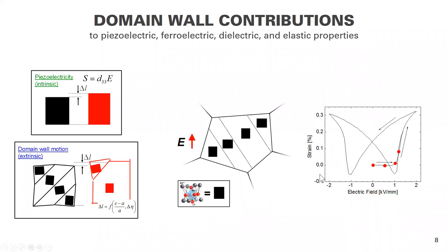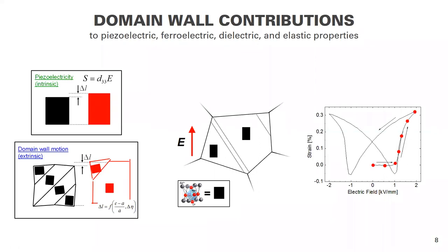And so with a little bit of electric field, not much happens. But as soon as you apply an electric field beyond the coercive field, most folks on the call know that you get ferroelectric switching. And this is a large amount of ferroelectric switching to the point where when you look at the microstructure, you have a very significant degree of domain reorientation. And then if you release the electric field and come back to the remnant state, you also have a preferred orientation in these domain structures. And what you can do is cycle it about weak fields and also appreciate that these domain walls continue to move and continue to contribute to properties.